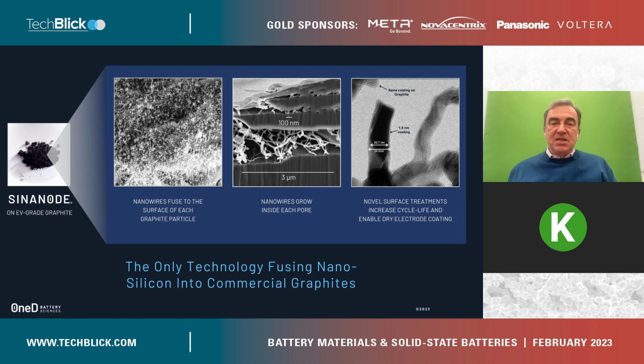And basically, the silicon is there because the silane gas that was used to produce those nanowires was able to get into those pores. And the nanowires grew by decomposition of the silane gas. Silane formula is SiH4, so it's one atom of silicon and four atoms of hydrogen. But when we do this, we end up with a powder that's a composite. There is no inactive material, and the powder comprises the graphite that was initially qualified by the EV cell maker, enhanced by the silicon nanowires, those little hair in white.